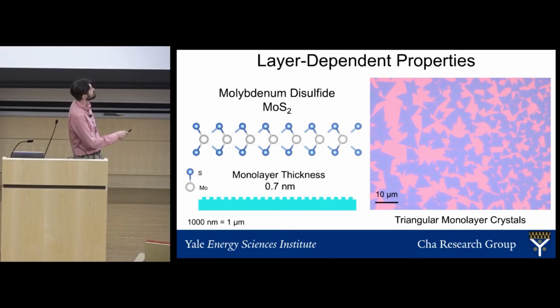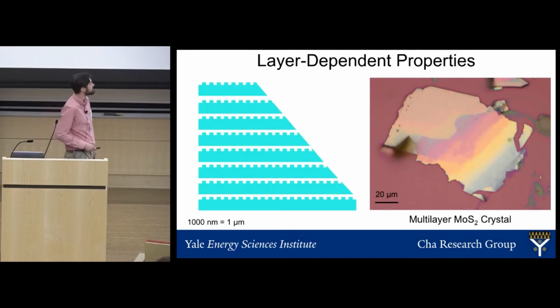So we see here, these are triangular crystals of molybdenum disulfide that I grew, and we can see that they're purple. But I can change their color just by changing how many layers are stacked on top of one another. So here's a bulk crystal that's had one edge shaved off, so we can see many different thicknesses at once.